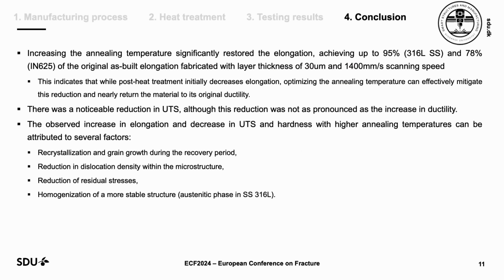And in conclusion, what I can say is that recrystallization and grain growth are one of the reasons for what we saw in the UTS and hardness, along with reduction in the dislocation density within the microstructure, and also reduction of the residual stresses in some cases. So there are residual stresses because of the heat process, right? In additive manufacturing, everything is about heat. It's about the melting, and we know that because of that, there are residual stresses. And what's the level of the residual stresses? Is it tensile or compressive? Of course, we didn't do any measurement, so I cannot say anything about our cases, but from other works, I can say that there are both, either tensile or compressive, and each one of those affects the part's macromechanical behavior. And also homogenization of a more stable structure when we do heat treatment. That happens specifically when we have a single phase, the austenitic phase in stainless steel 316L.